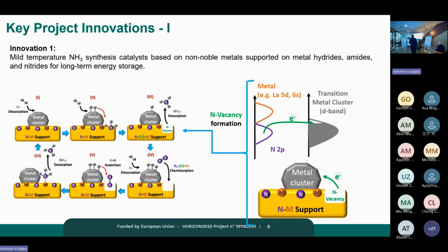Now, one of the limitations in this picture is the metal nitrides. In this particular case, things like cerium lanthanum nitrides are extremely sensitive to oxygen, and they will essentially not be scalable. So the objective of the Faria project is to move away from metal nitrides and use mixtures of materials, so things like metal oxonitrides, and that can allow us to operate these catalysts in the presence of things like water and ppms of oxygen and so on and so forth.